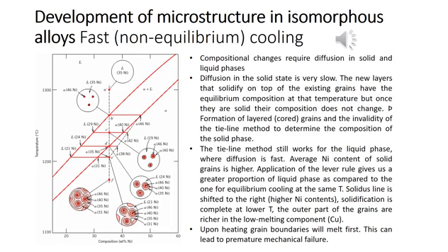Therefore, you produce a material that is made of many layers. So the first layer of our material was 46%, the second layer is at 40%. Then the new average, if you integrate those differential layers of different composition, you get a composition of 42% nickel. And if you move from C to D, a similar thing happens. And if you continue moving, you realize that there's a slight shift in the compositions to the right.